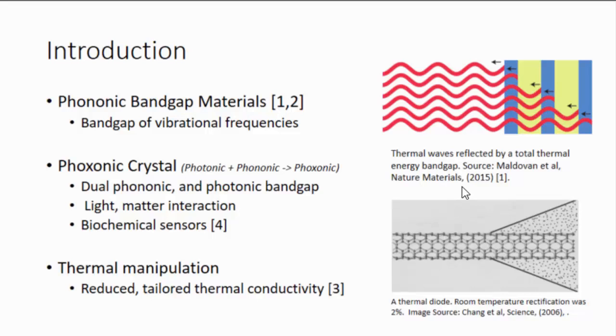So why am I going to measure the thermal conductivity of this material? Well, polymethyl methacrylate and silicon dioxide are both dielectric materials, so the primary thermal energy carrier in these materials is phonons. So by measuring the thermal conductivity of the material, I can then extrapolate or correlate what the phononic behavior of the crystal is.